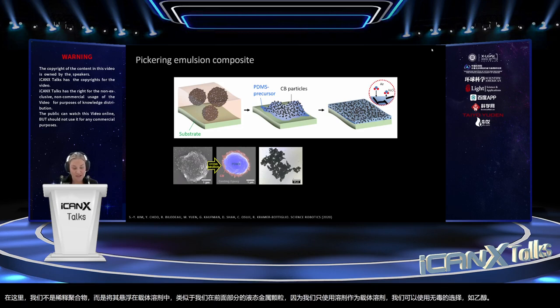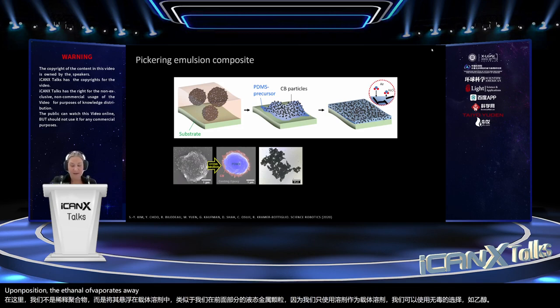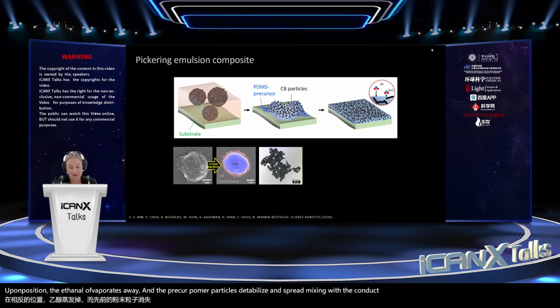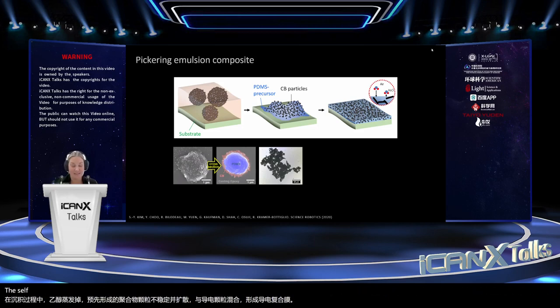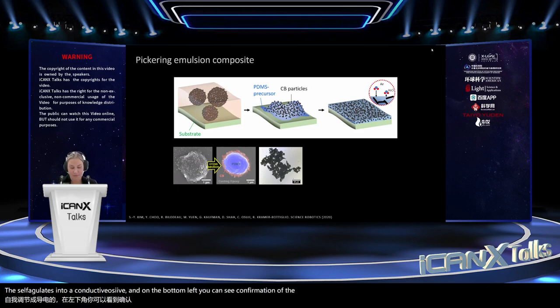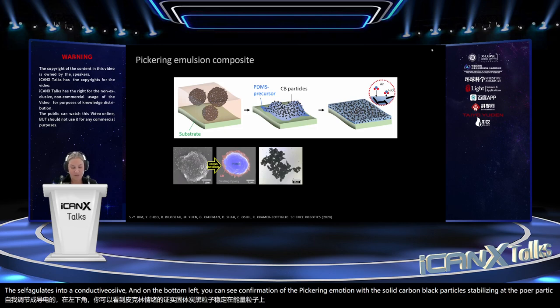Upon deposition, the ethanol evaporates away, and the pre-cure polymer particles destabilize and spread, mixing with the conductive particles as they spread to form a conductive composite film. So this self-coagulates into a conductive composite. And on the bottom left, you can see confirmation of the Pickering emulsion with the solid carbon black particles stabilizing at the polymer particle interface.